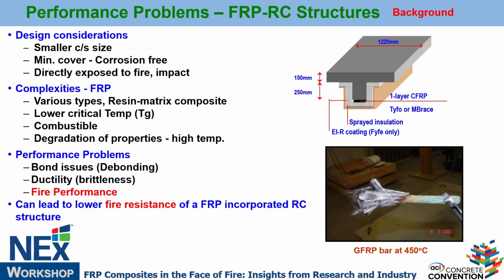Now, what's the difference when you put FRP into this concrete, either internally or externally? As you see, you are dealing with a smaller cross-section. FRP has very good strength properties at room temperature, so you design with a smaller cross-section. It's a combustible material, unlike your concrete and steel. FRP adds fuel to the fire, which you need to account for.